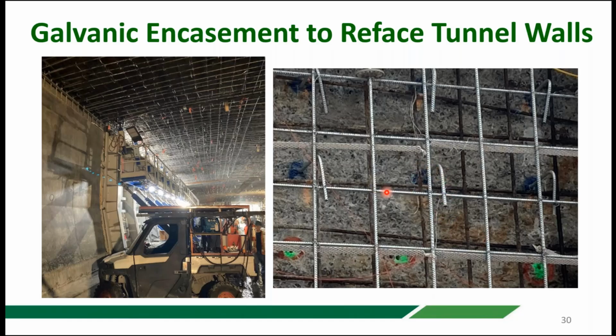They're putting in dowels and a new cage of reinforcing here. These are the anodes in this case. There's one there, there's another one there, here's another one down here. They're kind of put in on a grid pattern over the wall area. They're using these massive forms, and they're basically forming a 100-foot long section of wall all in one section. They have hydraulics and a rail on the bottom for moving along the length of the tunnel. They set them in place, and then they pump the basically self-consolidating concrete in behind the form.